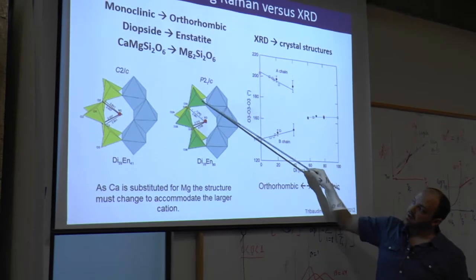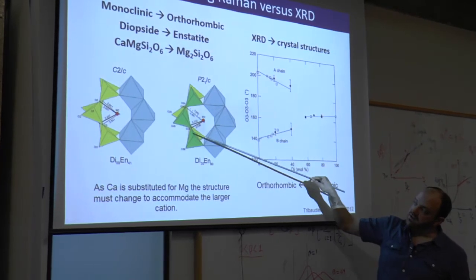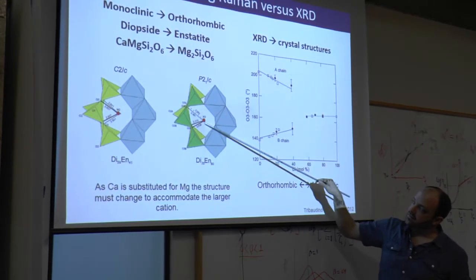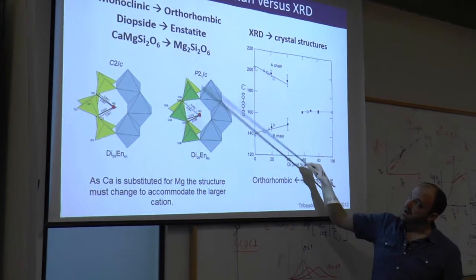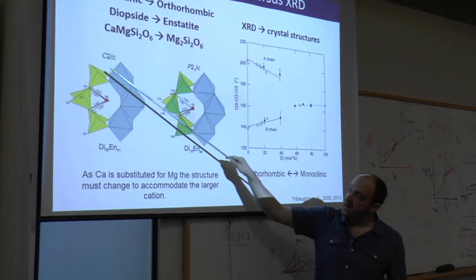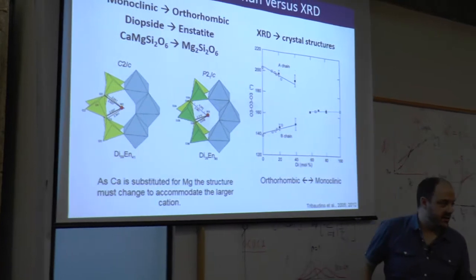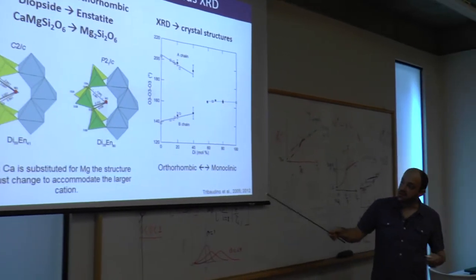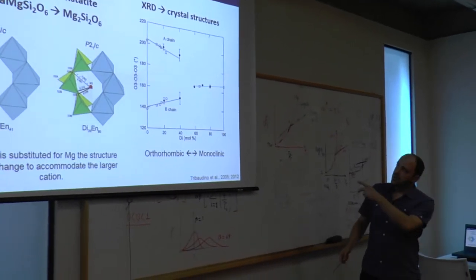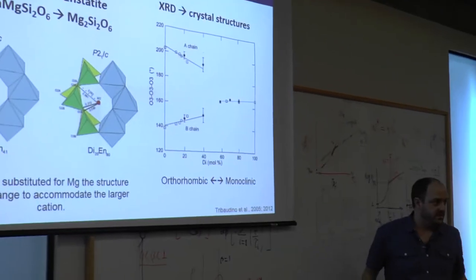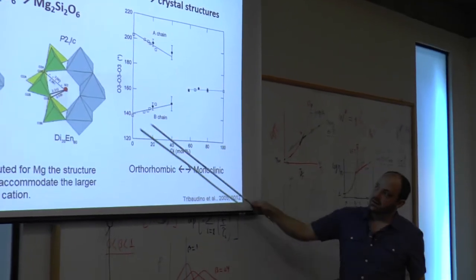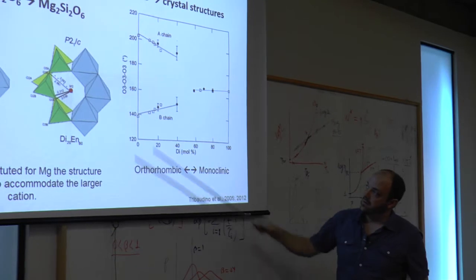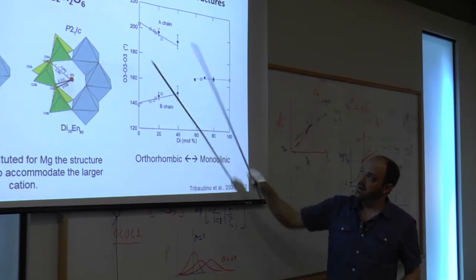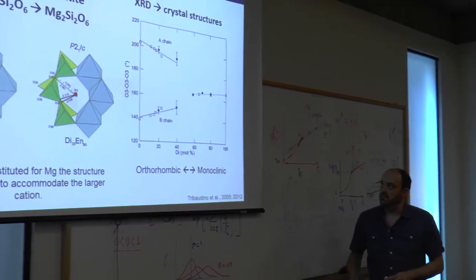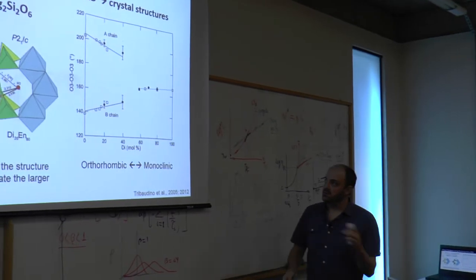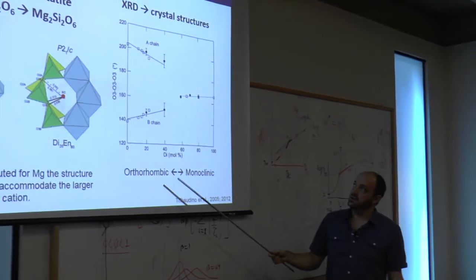So in orthorhombic, we have one chain with slightly different angles and slightly different bond distances to the magnesium in here. In the other case, we have two chains that actually have the same intertetrahedral angles. This is from XRD, where they actually measured the oxygen-oxygen angle. I'm not so much of a mineralogist, so I won't go into that, but it's a measure of this intertetrahedral angle.